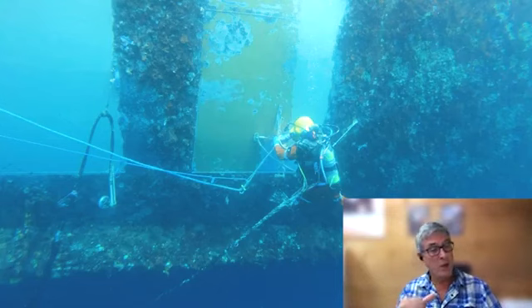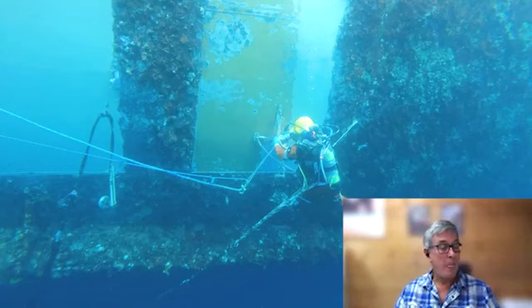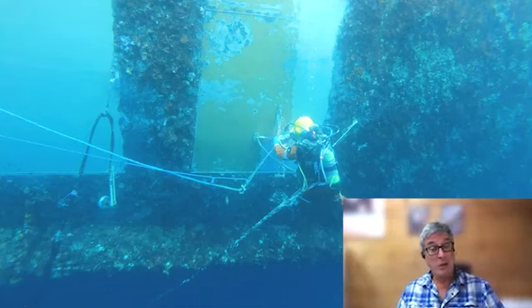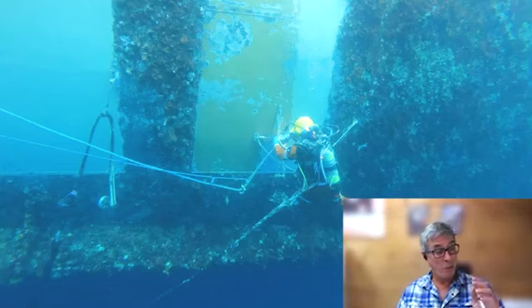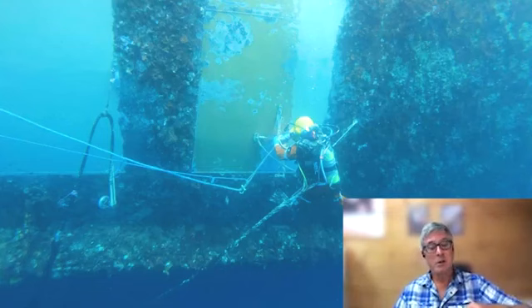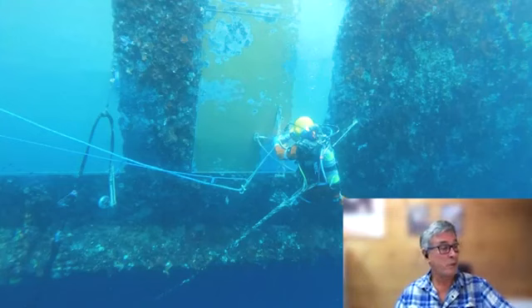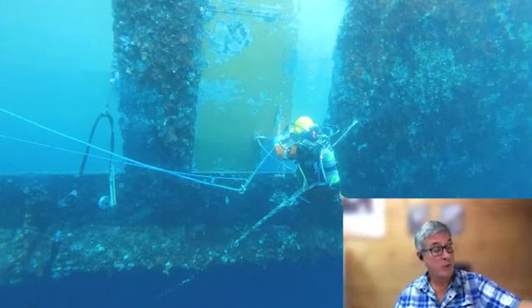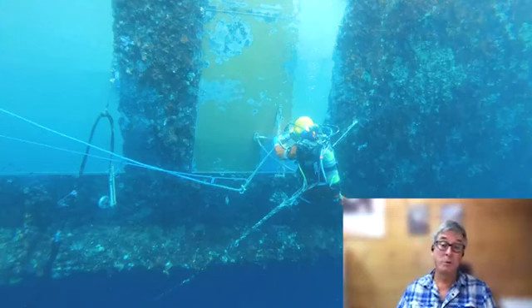But if the diver uses his training and applies the coating correctly, we regularly use a wet film thickness gauge to check the coating thickness. But with practice, after you've done that 10 or 20 times in your painting over an area like this, you know that you're going to have 250 to 300 microns of coating over the existing coating, which is well more than what was there in the first place.